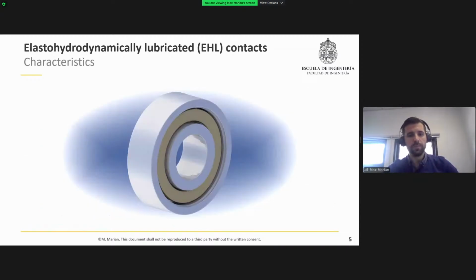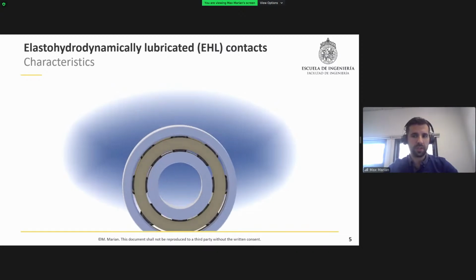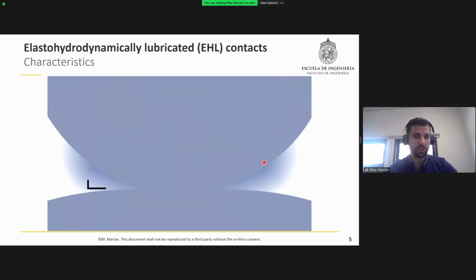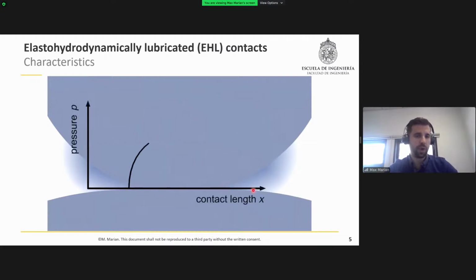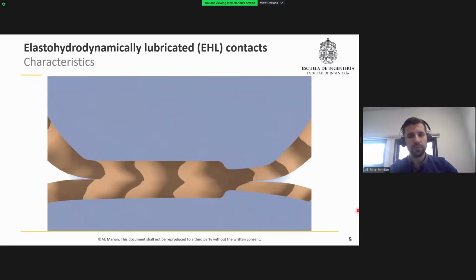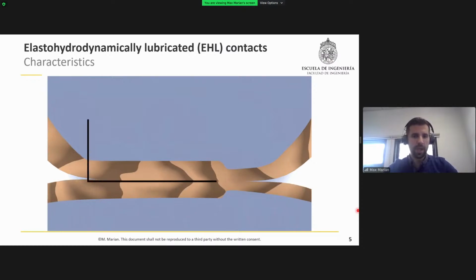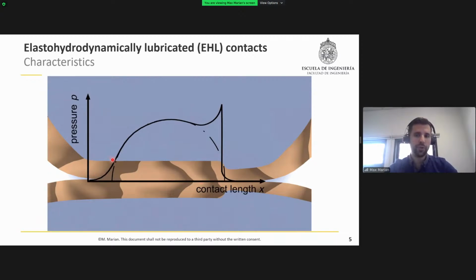In the case of more heavily loaded contacts, where pressures can reach up to 4 gigapascal, which roughly corresponds to the load of 7 African elephants standing on the area of a human thumbnail, as we have, for example, in rolling bearings, there's some elastic deformation of the contacting partners that adheres to concentrated contact geometry, and this can generally be described by the Hertzian theory and the Hertzian pressure. Due to a lubricant, there's also a superimposed formation of hydrodynamic pressure. And in the area of contact inlet, compared to the Hertzian pressure distribution, we generally get an earlier pressure increase, which occurs due to the lubricant compression.